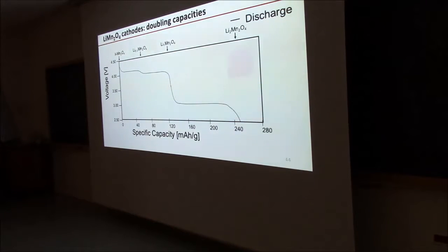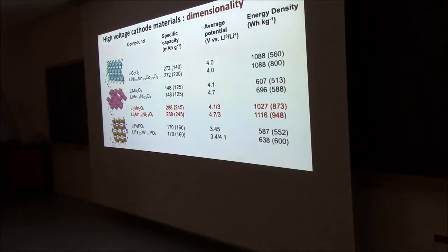This material will allow that. The problem is, it will deform so much, if you do charging and discharging, you get distortions, that you can only do this a couple of cycles and then it's gone. You cannot cycle this for long. People know that this is possible, but they will never do that because you will really damage it. But why would you do that? You take your lithium manganese oxide, you double your lithium, you can see the increase in the capacity, and the voltages are the same. So then you would be able to achieve capacities which are close to lithium cobalt oxide. And you double the amount of lithium.